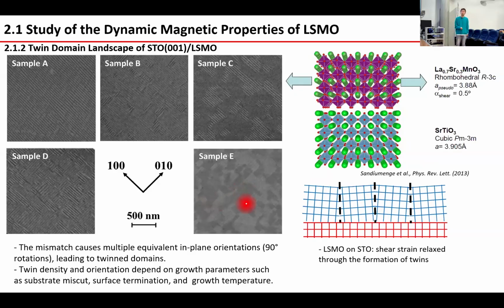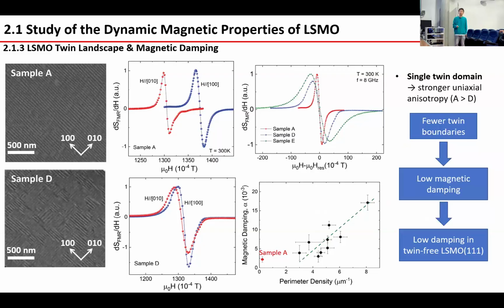And the twin boundary density and the orientation depend on the growth parameters, such as substrate miscuts, surface terminations, and the growth temperatures. So it shows distinctive samples where sample A shows a single twin domain, and sample D shows two in-plane orientations of the twin structure. We measure the ferromagnetic resonance along the 100 and 010 orientations, where sample A shows a distinctive resonance field, with the 100 relatively higher than the other. However, sample D shows the resonance field is quite similar. So it's indicating that the single twin structure has uniaxial anisotropy along the 100 orientation.